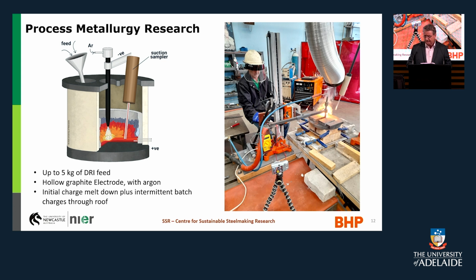So that's what we've tried to do in our test work at University of Newcastle. We started small, which I did talk about a couple of years ago at the last Newcastle symposium. We started out with wire feeding in a welding circuit type operation, but quite quickly we progressed to trying to work with an actual carbon electrode, DC electrode, single electrode, and so we're now up to around 5 or 6 kilograms as our charge size, and we're able to do it quite successfully.